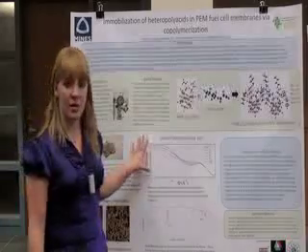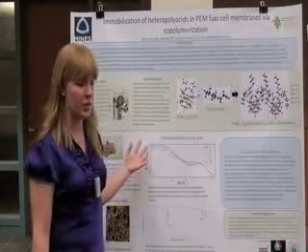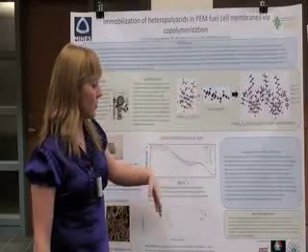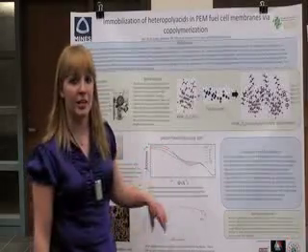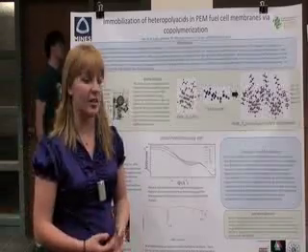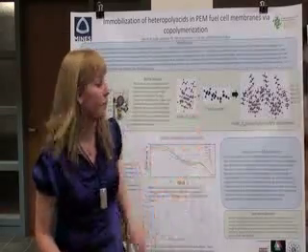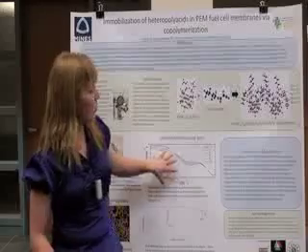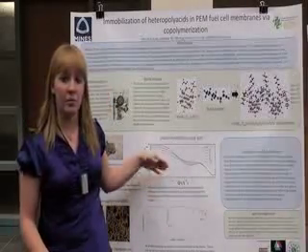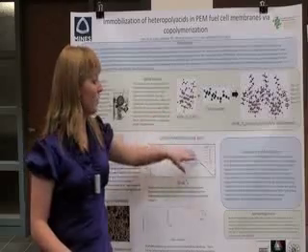This is a SAXS image that we got from the Advanced Photon Source at Argonne National Lab, and we took a polyPOM 25, meaning it has 25% heteropolyacid and then 75% butyl acrylate in it. And it shows how the morphology of this membrane will change depending on the relative humidity.